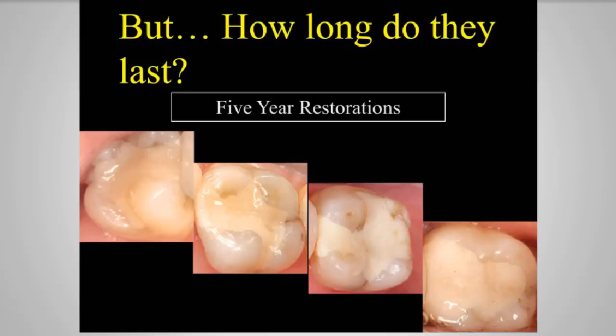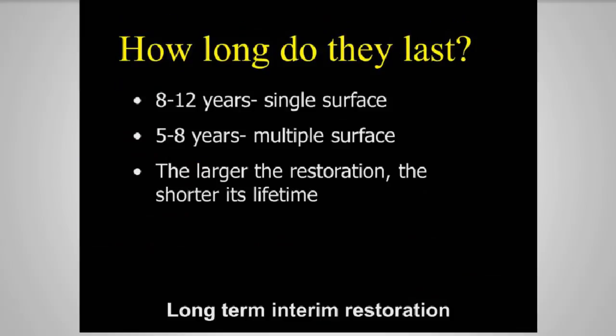The problem I find with composite is it's so close to the pulp because, as you know, as you go deeper on the root surface, you're closer to the pulp. And people would say that filling you put in just killing me no matter what I did. If I do it with a pure glass ionomer, it seems to significantly reduce the postoperative sensitivity they get. So how long do these things last? This is my guide only. I think 8 to 12 years for a single surface, 5 to 8 for a multiple surface. Obviously, the larger it is, the shorter period it's going to last.